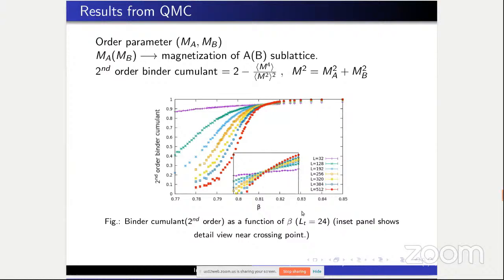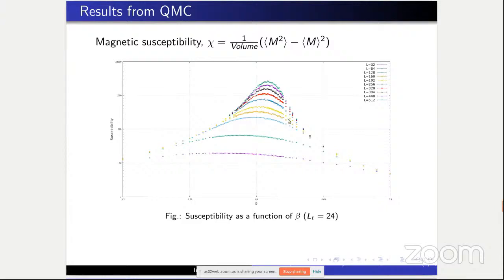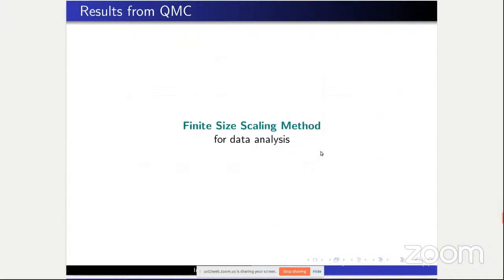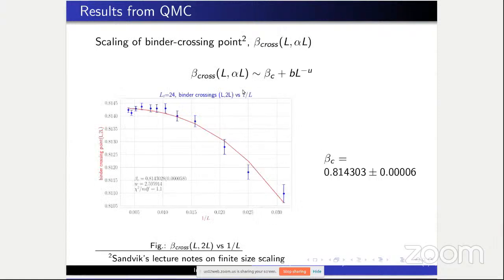So there is a thermodynamic phase transition in this model, and this is susceptibility versus beta graphs for various system sizes. Now we have used the finite size scaling method to calculate the critical quantities. So the Binder crossing point beta cross between the system size L and alpha L, where alpha is some integer other than 1, follows this scaling law: beta cross L alpha L equals beta C plus B L to the power minus U. So this is the Binder crossing point versus 1 by L graph.